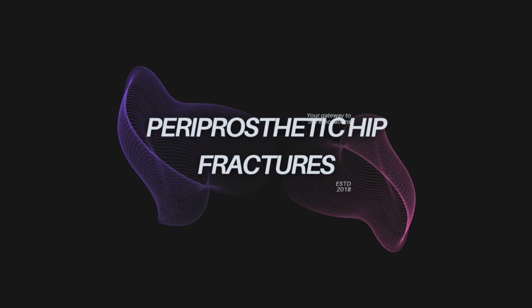If the stem is seated and those stresses have achieved press-fit stability before the fracture occurs, you are testing the actual construct in its final position. If it holds, it holds. But a fractured cylinder is not an intact cylinder. When you have an uncemented stem, the long-term stability relies on osteointegration. The bone literally has to grow physically into the microscopic porous coating of the titanium implant.